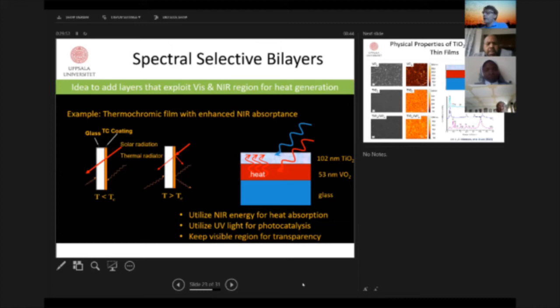I have sketched one possibility here. If you place the photocatalyst on top here, which is transparent for the rest of the solar light, and then you have a heat-absorbing film underneath, which becomes hot, then you will heat this photocatalyst and improve the surface kinetics, which is of course in many cases Arrhenius type behavior, so exponential in terms of temperature.